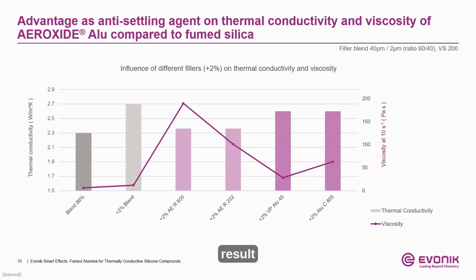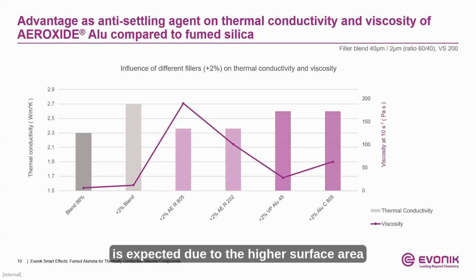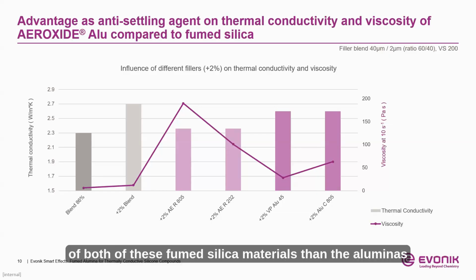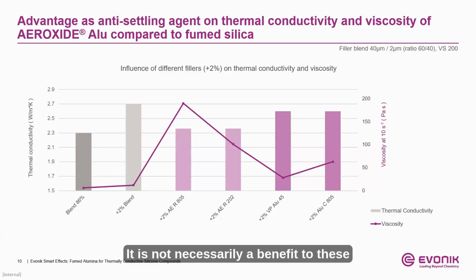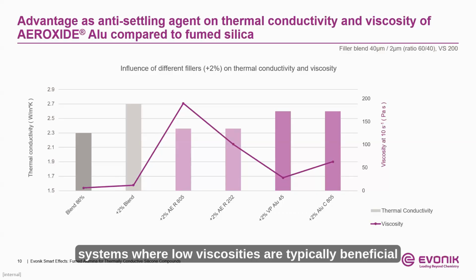While this result is expected, due to the higher surface area of both of these fumed silica materials than the aluminas, it shows a rheological performance that is typically what you would want to see when using fumed silica. It is not necessarily a benefit to these systems, where low viscosities are typically beneficial for processing and application purposes. Perhaps more importantly, the fumed silica actually has a deleterious effect on the overall thermal conductivity of the system.